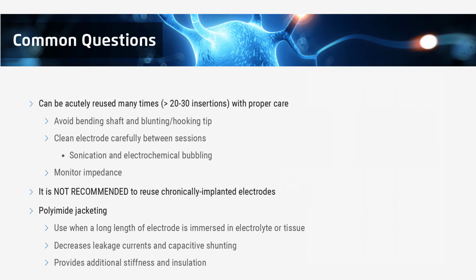You'll know that it's working because it'll start creating some pretty vigorous bubbling on the surface. Again, this is the hydrolysis that I mentioned earlier. This bubbling tends to knock off oxidation or any other crust that has developed on the electrode surfaces. We've noted that it's a common complaint among customers, especially those that are storing their electrodes or arrays for long periods of time, that when they actually open their array and measure the impedance, it's much higher than the impedance that they specified. A lot of times this is because, even though the materials are mostly noble, they do corrode over time. Typically, we suggest that they do an electrochemical bubbling process, and they note that the impedance immediately will go back down to the specified values.